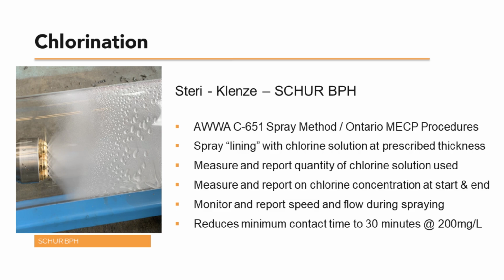In addition, because higher concentrations of chlorine are used in the spray method, contact time may be reduced to as little as 30 minutes under the AWWA and Ministry of Environment of Ontario procedures, whereas normal disinfection times can be as much as 24 hours. The use of the Steri-Klenze system is one more step where we've been able to compress the time required to reinstate the water main. Various technologies have been combined to deliver spray-in-place lining and disinfection processes to deliver same-day return to service.